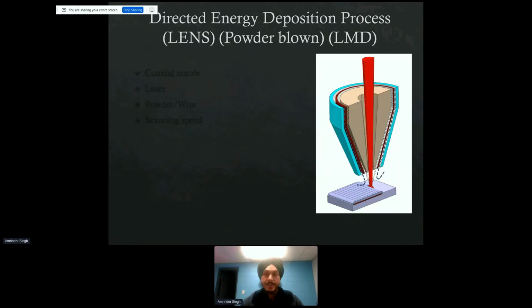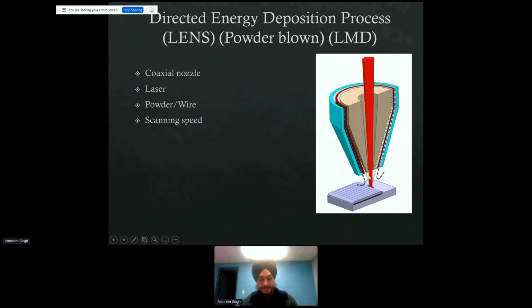So this is what we are specialized in, the directed energy deposition process. What we do is, we have a coaxial nozzle, which we can see right there. And then the laser comes from the center of the nozzle. Powder comes from this cone in a conical shape. And then the laser comes from the center, hits the substrate, creates a melt pool, powder goes into the melt pool, and as soon as the whole system starts moving to one side, that melt pool becomes a solidified bead, creating a single continuous bead. And then in this way, you can do cladding or make parts.